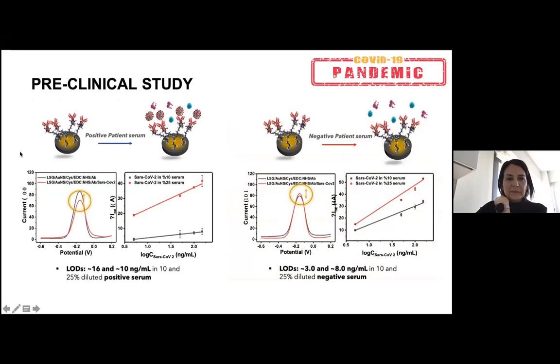So this is our surface, when we use the positive serum or positive samples and negative patient samples. As you can see, there is a binding, and as a result of this binding and interaction, these are DPV signals obtained in the presence of the redox probe hexacyanoferrate. This is in the presence and absence of sample. You can see the reduction in the electrochemical signal. And in the case of negative patient serum, you can see the difference. And when we compare the two, this is negative and this is positive, we can say that it works successfully.